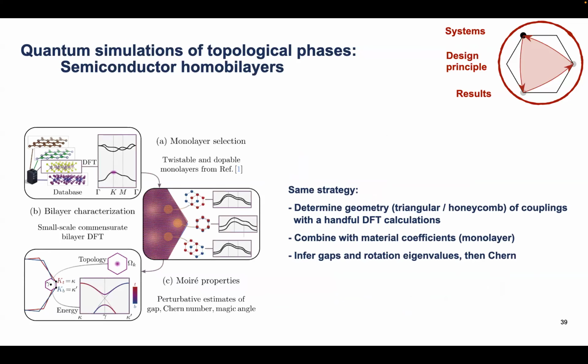So you can use the same strategy for the twisted homobilayers. Then it's slightly more abstract, but the same strategy holds. So what you want to know is the geometry of the superlattice Hamiltonian, so what will be the harmonics that will couple the corners of the Brillouin zone. And for that, you just have to ask how big is the interlayer tunneling, for instance, at specific points of my Moiré Brillouin zone. So if I know the tunneling at that point where the two lattices are on top of one another, or when they are shifted by a third of a lattice constant, then I can determine the first few harmonics of my superlattice potential. I combine it with the material coefficient as I did before, and then using my symmetry indicator formula, I know if there are vortices or not, and I count the number of vortices, I get the Chern number.